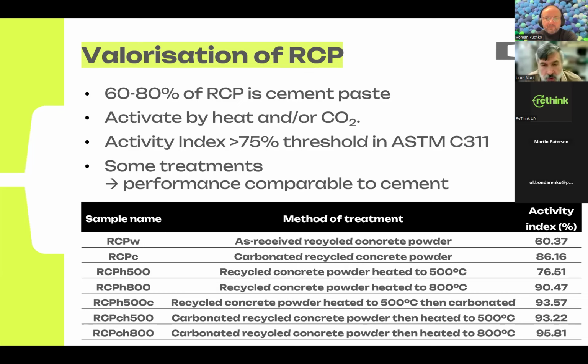strips calcium out of your cement paste, converts your recycled cement paste to a mixture of calcium carbonate and an aluminosilicate that can act as what's known as a supplementary cementitious material. So it can be blended with cement, producing additional cementitious binder. Okay, and the standard test to assess the performance of a supplementary cementitious material is what's known as an activity index. You take 80% cement, 20% of your material, and if the compressive strength is greater than 75% of that of a reference mix, it's considered to be a suitable cement replacement.